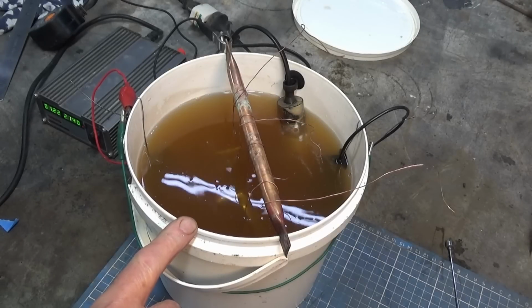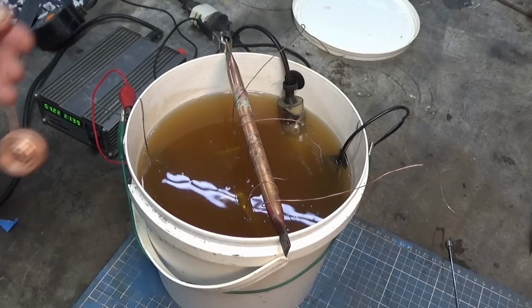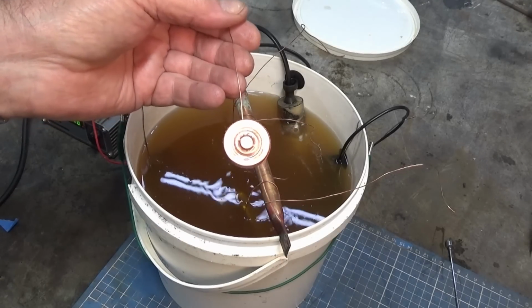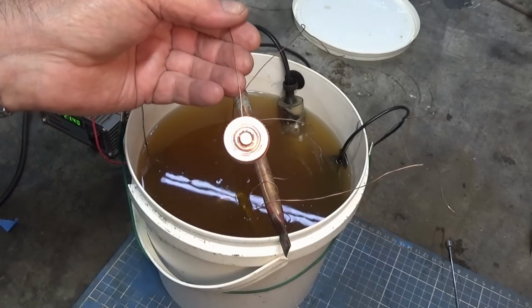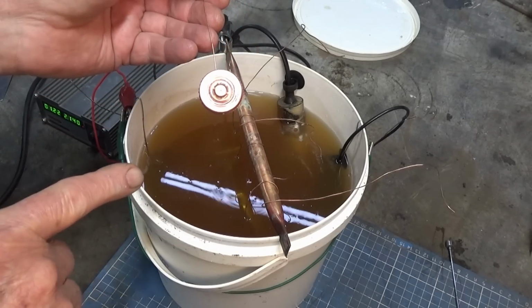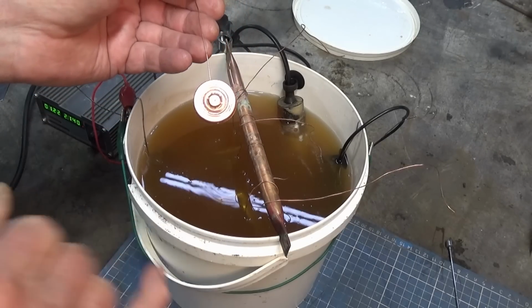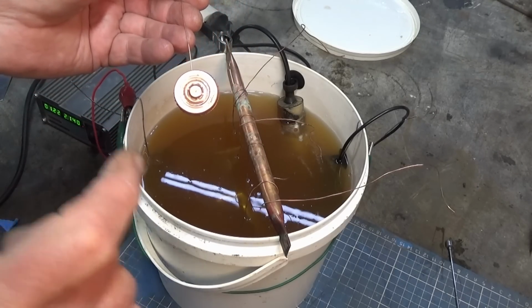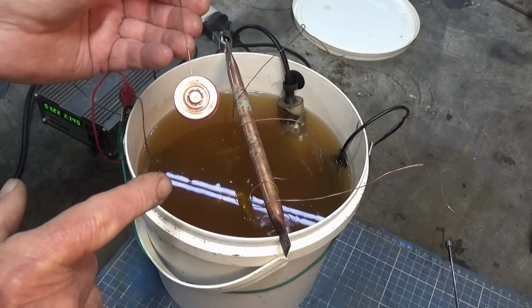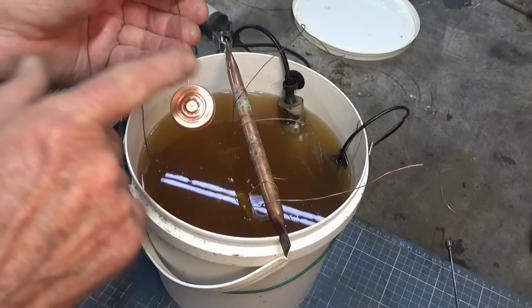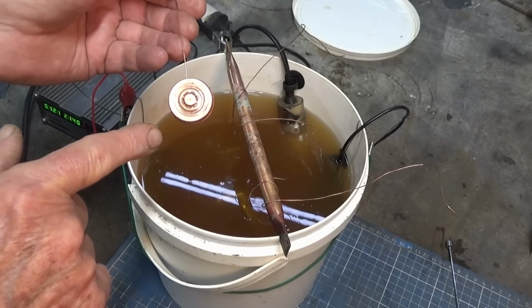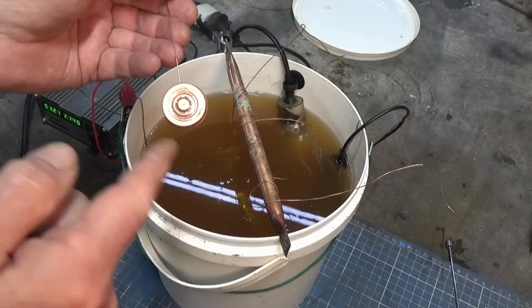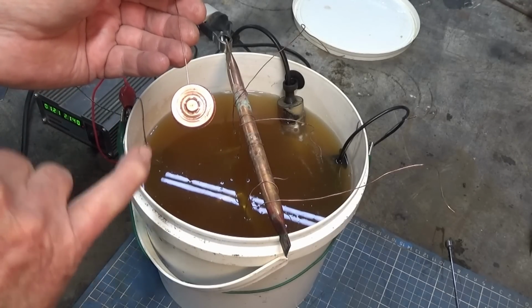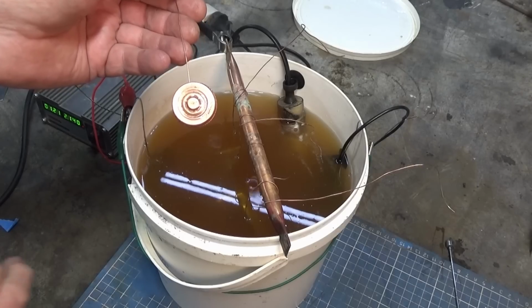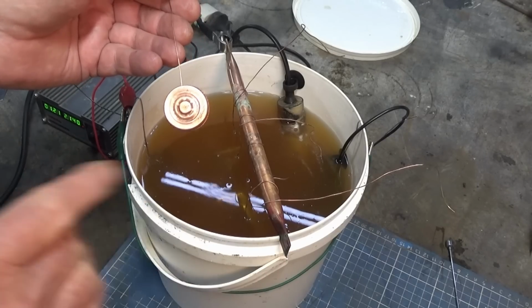Okay, it's time for an update now. I've totally chickened out here and I'm going to zinc plate these parts. So I've got one of the hubcaps cleaned up. I'll put it in and I'll show you what it looks like. Now, it's not ideal. Zinc is a little bit more forgiving than the nickel cobalt, and it is covering these parts even though they've got some chrome showing through and some bare steel and some copper. So that's what I've decided to go with, and it's going to be shiny, but it won't be perfect.